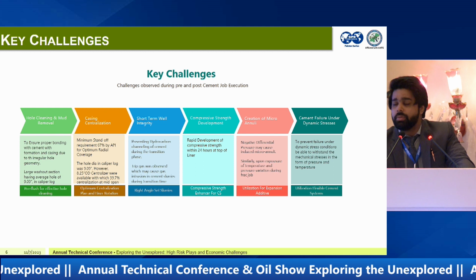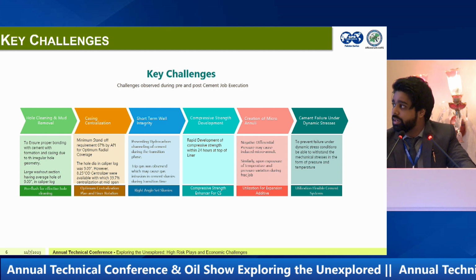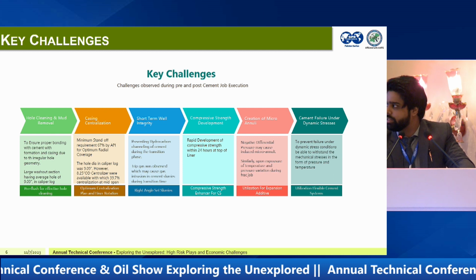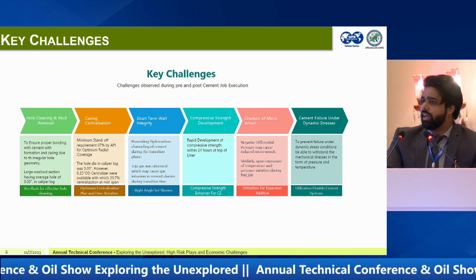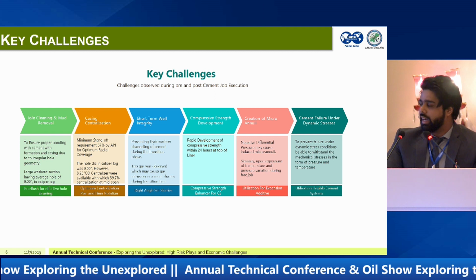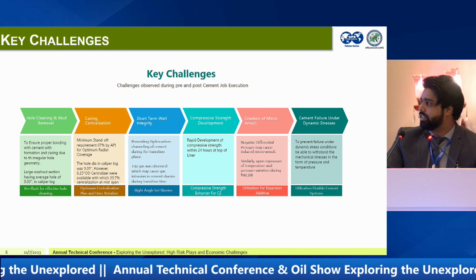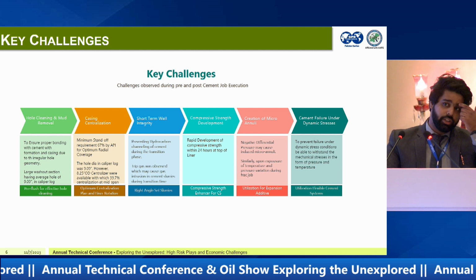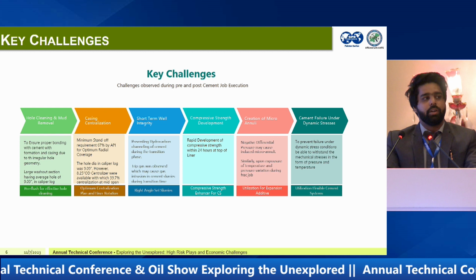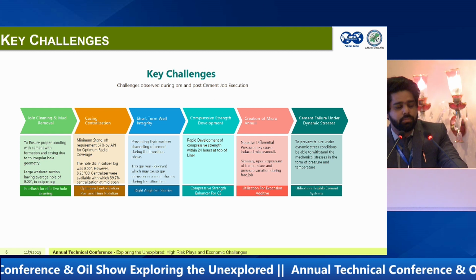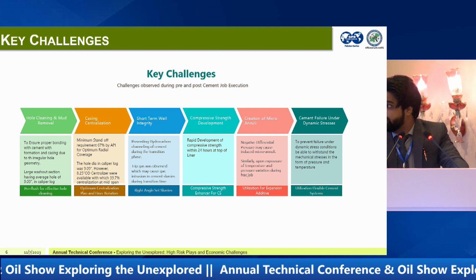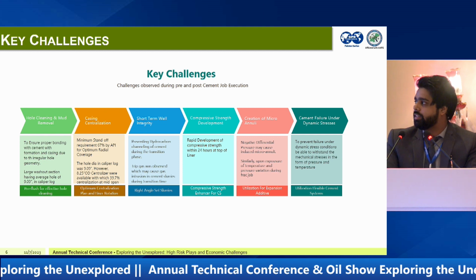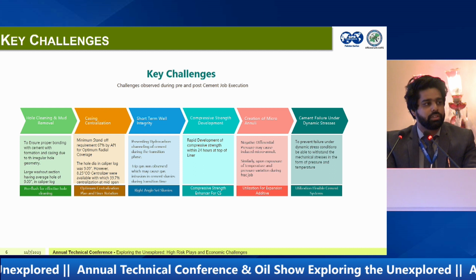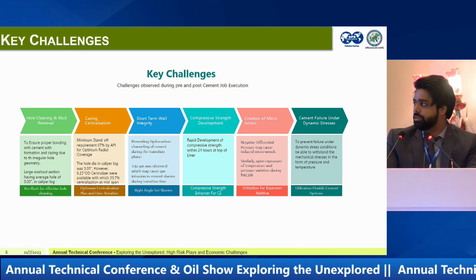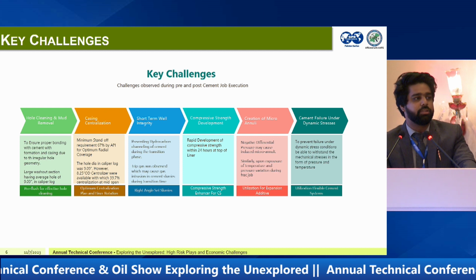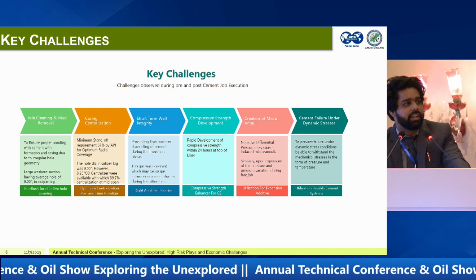For performing any cement job, hole cleaning and mud removal bear great importance. While performing the job in the southern region of Pakistan, we had a challenge of irregular hole geometry due to large washouts in the 7-inch section, and from the caliper log we evaluated that 9.09 inches was the hole diameter. So, in order to have good hole cleaning, we proposed Well Wash, a surfactant-based solution, and we incorporated spacers so that we have good and effective hole cleaning.